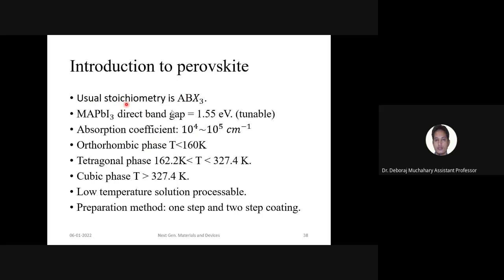The introduction to perovskite: this is the chemical structure we know, ABX3. A is something like methyl ammonium or formamidinium. Then B is something like lead, and some other materials also, like tin or others. And X is a halide, halogens like chlorine, bromine, iodine. Their band gap is tunable, so you can tune the band gap. It's approximately 1.55 for this, but you can tune it with the help of the chemical structure. Then the absorption coefficient is quite high, around 10 to the power 4 to 10 to the power 5, so it's a good absorber of light. Now it has three phases. According to the temperature, below 160 you will get the orthorhombic phase.